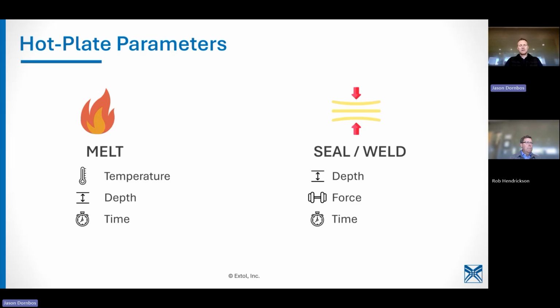Yeah. So there's lots of different parameters here, but some of the main important ones are you want to control the temperature and the depth and how long you're in contact with the heated tool. That is affecting how much heat you're putting in. And then you have the seal or the weld phase where we can control the depth, how far we're pushing those parts into each other, the forces that we're using to do that, and how long we're holding it. That's all the pressure parameters that really matter the most.